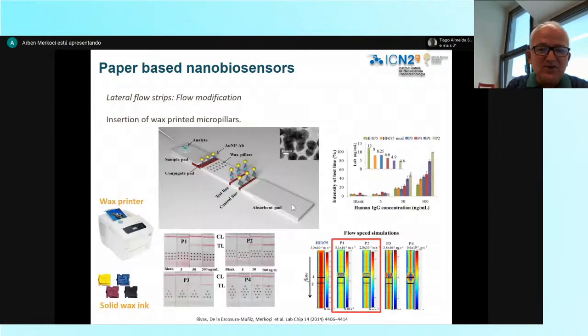But instead of changing the geometry, what we did is introduce some wax pillars onto the paper. You can see here it's the same lateral flow, but now in the part of the paper between the conjugation pad and the test and control line, we printed with a wax printer some pillars, trying to find and optimize their distribution in a way that we can do the same as we did with the change of the geometry of the paper. You can imagine that introducing these pillars into the paper is going to disturb the microfluidics. So the microfluidics, in fact, is changing.